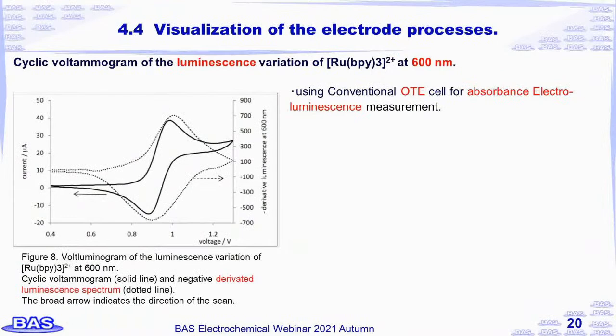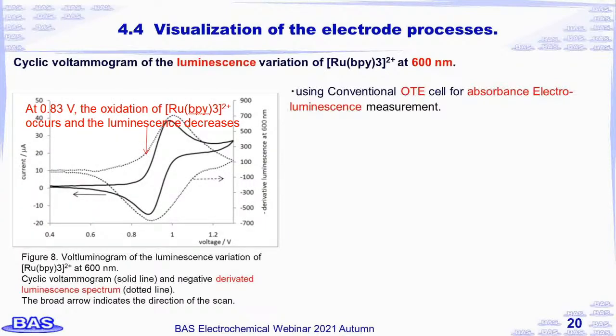Figure 8 shows the cyclic voltammogram and the luminescence variation of tris bipyridine ruthenium at 600 nanometers. A conventional OTE cell for absorption and electroluminescence measurement was used. The solid line is the cyclic voltammogram and the dotted line is the derivative luminescence spectrum. At 0.83 volt, the oxidation of tris bipyridine ruthenium occurs and the luminescence decreases.